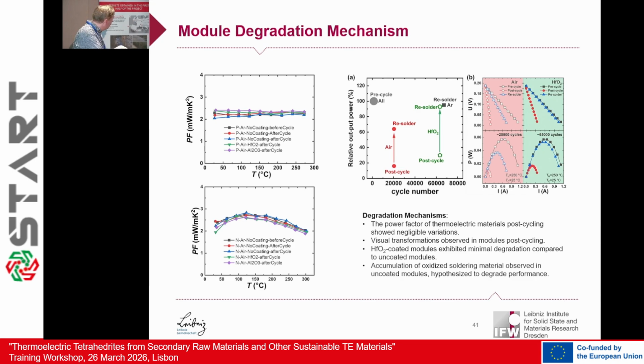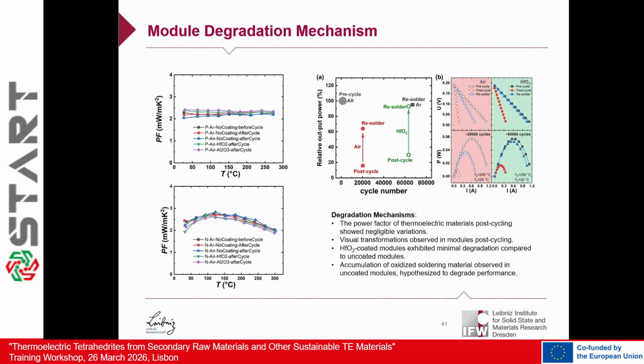This also shows all this testing with soldering, unsoldering, and operating with different coatings. You can see this material is rather stable. The weakest point in the whole study is the soldering. If you redo the resoldering, you get back to the same performance you had at the beginning when you have, for example, the hafnium oxide coating. This gives a very good performance.